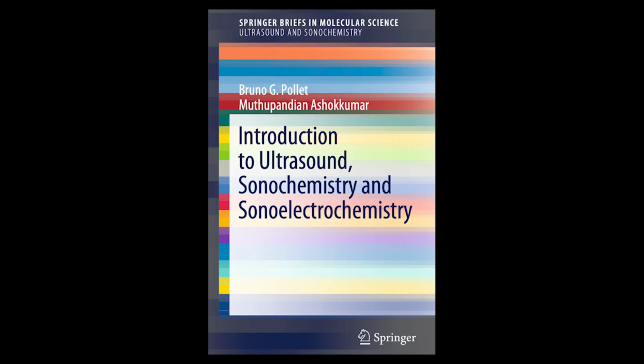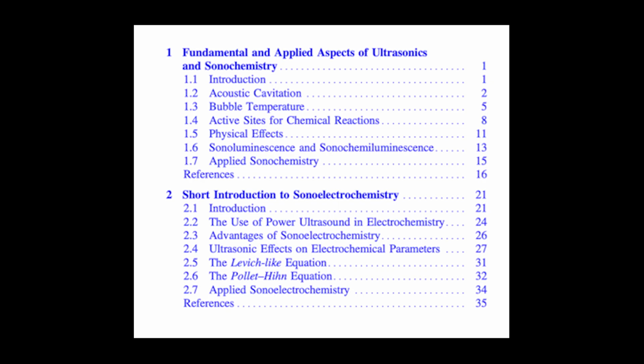Remember that ~1900K interfacial hot zone. Even if the bulk is cool, the electrode surface itself might be experiencing transient high temperatures during cavitation collapse nearby. And higher temperatures generally make chemical reactions go faster, including electron transfer. So faster kinetics due to local heat. Makes sense. But you said conflicting results.